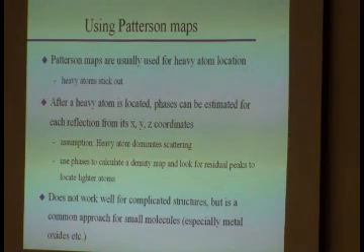And that goes back to, remember how we said, every peak in the Patterson, the height is proportional to z times z prime, where z was the atomic number of the element, equal to the number of electrons. The heaviest atom will obviously have the highest z, and the height of the peak that corresponds to the distance of that atom to its symmetry equivalents is going to be z squared. Okay?